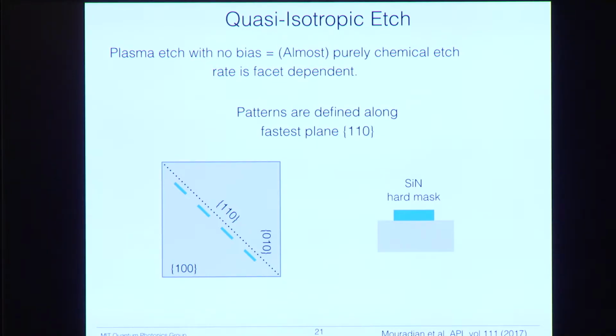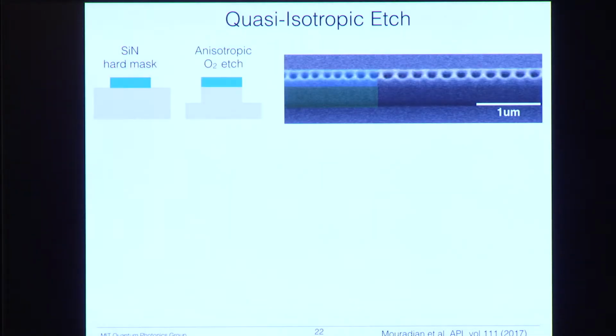So to do this, we use a silicon nitride hard mask on top of our big bulk diamond. When I say big, I mean a couple millimeters, so it's still pretty small. But at least you can use tweezers and stuff to pick it up. We start with a silicon nitride hard mask that we pattern with ZEP and the EBL. We then do an anisotropic oxygen etch. So this is an etch with a bias, and we can get nice straight side walls. It doesn't degrade our silicon nitride mask too much. So you can see here in SEM, this is our silicon nitride mask and the diamond underneath.